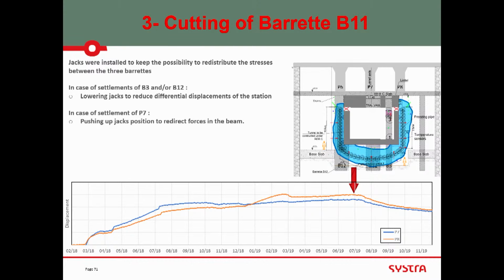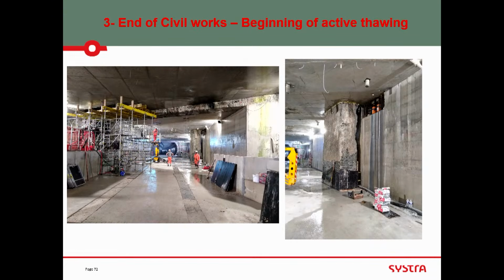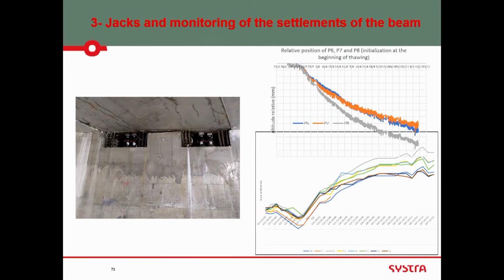So we adapted the roof until there was no freezing area, excess pore water pressure was dissipated, and then it was sealed, and the contractor had finished, and the guarantee started at this point. So you can see the jacks, the barrette, which is on the side. Again, the jack, and we were able, in fact, to lift the box above to compensate for the vertical displacement. You see the joint of the slab between fixed top slab and the moving top slab, just at the location of the barrette which was cut.